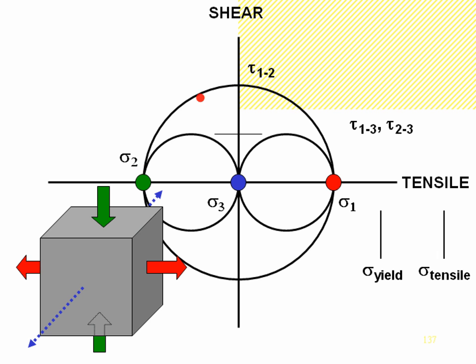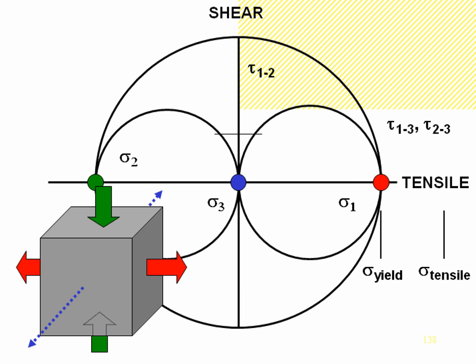Now, if I increase sigma 1, of course, I have to increase the magnitude of sigma 2 in compression. Now I'm up to the yield strength of the material. My other shear planes are finally getting up to the critical shear stress. But look at what's been happening here: lots of deformation before I even got to the yield strength.